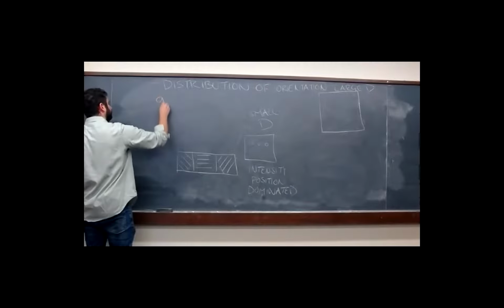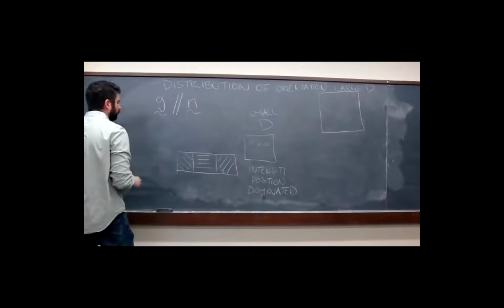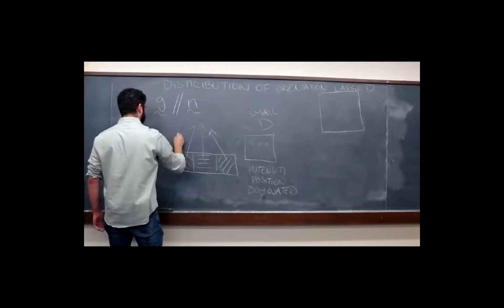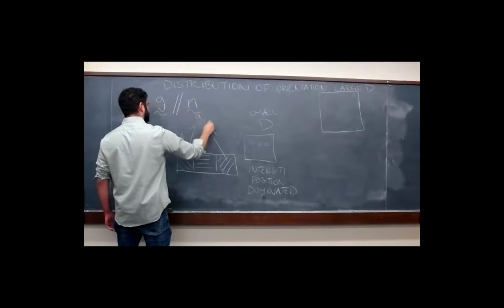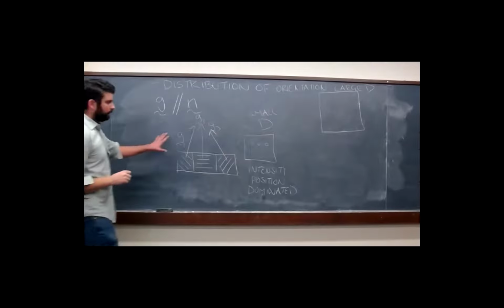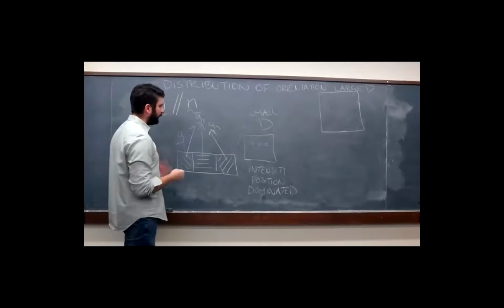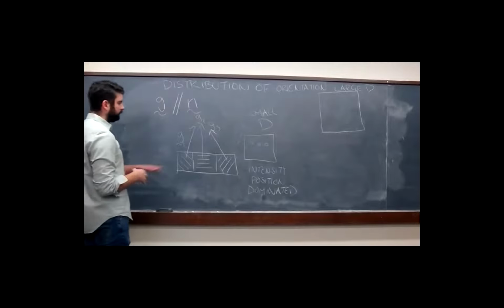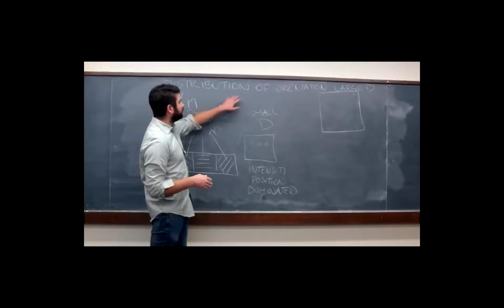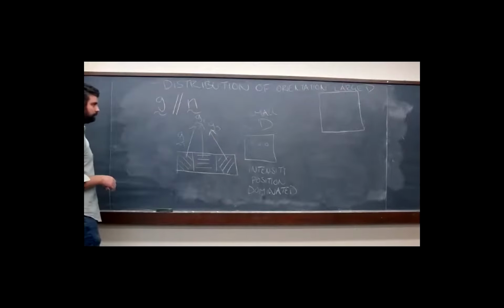And what we remember is that the reciprocal lattice vectors are also parallel to the lattice plane normals. So again, if we're in close, the angle at which diffracted intensity is emitted doesn't really matter too much, because we're dominated by the positions of these crystallites in space. So we get the same effect between strain and orientation. If we're in close, we're insensitive to both these effects.